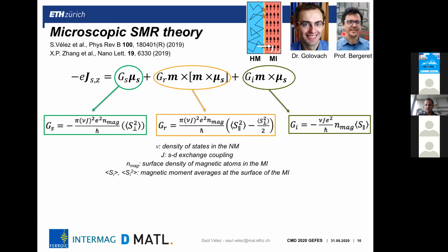So in collaboration with Professor Bergeret and Dr. Golovach, we addressed the microscopic origin of these components, and we found explicit equations that relate the spin mixing conductance to the interface properties of the material. So actually, we have the density of states of the non-magnetic metal. We also have the s-d exchange coupling at the interface, and also the surface magnetism of the magnetic insulator. And these parameters here relate to the magnetic moments of the systems, either parallel or perpendicular to the magnetic field applied.